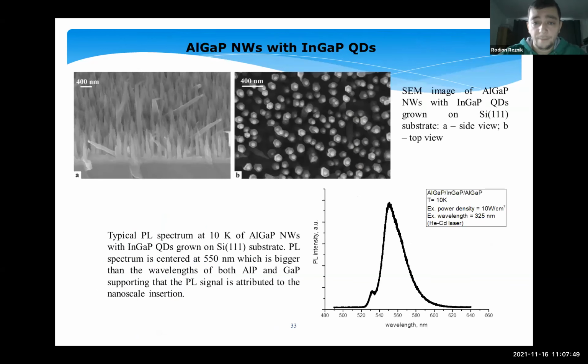Also, we wanted to use other materials to increase the number of applications again, and have grown aluminium gallium phosphide nanowires with indium gallium phosphide quantum dots. It's some kind of new result as well. So you can see in the SEM we have not so simple morphology of the nanowires. We think this is because of the indium participation in the growth; the nanowires can change direction in some cases.